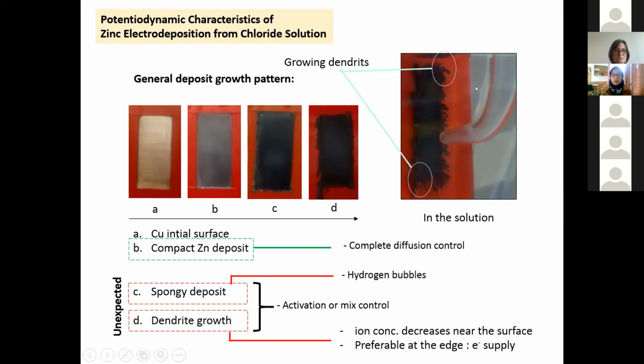In the previous result, we know the pattern of growth of zinc deposition from chloride solution is, as usual in other zinc depositions, that it starts with dense zinc, then it becomes spongy, and then starts to become dendritic. The spongy stage is proof that hydrogen evolution is there, but then the hydrogen evolution worsens and makes some dendritic pattern, and this is also because of decreasing zinc availability near the surface.